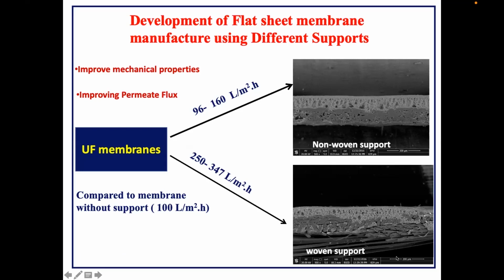Here we used a flat sheet for ultrafiltration. In ultrafiltration, the support improves the mechanical properties and improves the permeate flux. We compared the membrane without support, about 100, and here 200 or 300 almost LMH. So this means that the woven support gives us a high flux rate, reaching the national or international flux rate per square meter.